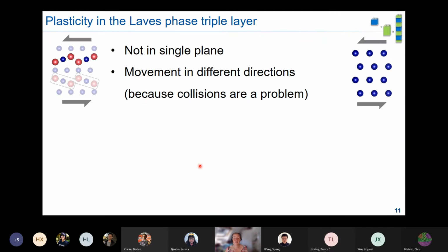And there are a few difficulties with this. All of a sudden, slip is no longer happening in one single plane. It's two adjacent planes, and the atoms also move in two different directions. So also the normal kind of modeling strategies that we use, like a gamma surface, kind of go out the window in terms of understanding these.